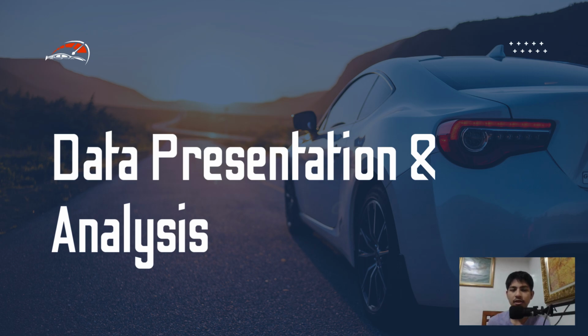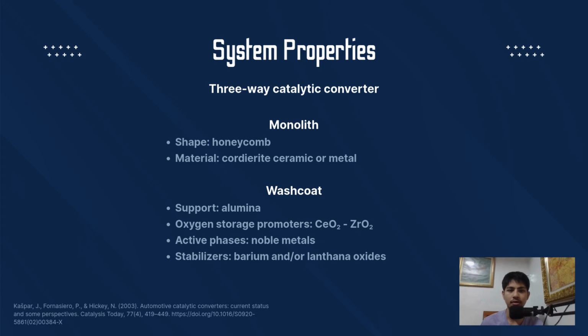Good day. For the data presentation, we are investigating monolithic catalysts in automotive exhaust systems based on the comprehensive research by Kaspar, Fornasiero, and Hickey. The core of a modern converter is a honeycomb-shaped ceramic or metallic monolith substrate coated with a porous alumina washcoat, which supports active noble metals such as platinum, palladium, and rhodium, alongside ceria-zirconia oxygen storage promoters and barium or lanthana oxide stabilizers.